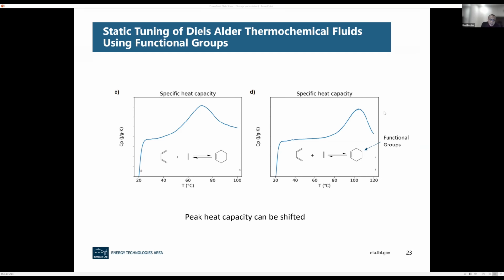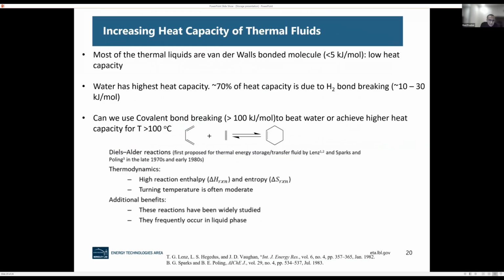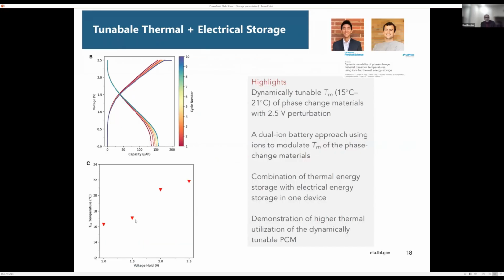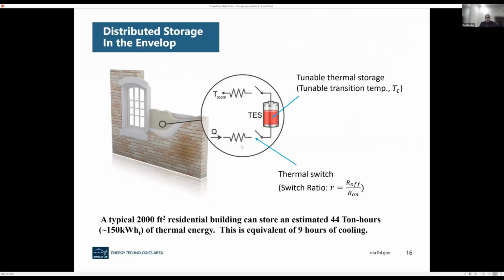Yeah, basically, we measure this in a DSC, where the accuracy is plus minus 0.2 degrees. So we can see that it's way beyond. But we are also developing a switch here, which I didn't talk about. We are in the process of submitting the paper, where we have shown that the switch ratio is almost 20:1 in terms of the conductance of the switch. So it's completely insulating when it is in the off state and very conducting in the on state.